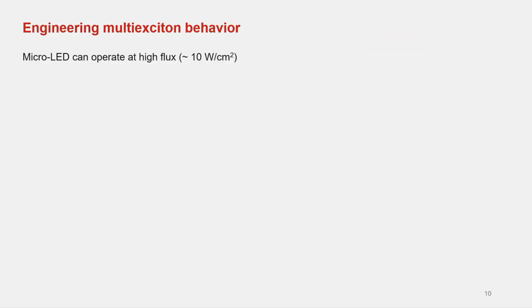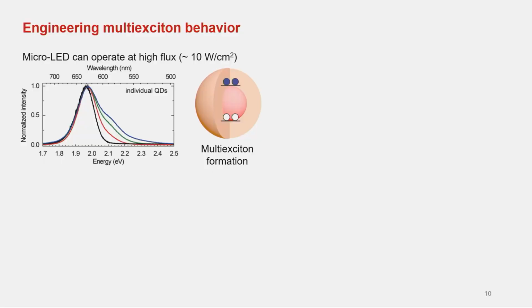So the next part is about spectroscopy. There are several related problems that we think we should consider when we utilize these quantum dots for micro LED applications. First, people reported that on the micro LED you have a really high incoming photon flux, which probably reaches around 10 watts per centimeter squared. And it's known in the quantum dot field that if you have a really high incoming flux of excitation light, you will see another peak come out on the side, which is actually the formation of multi-excitons and their emission.